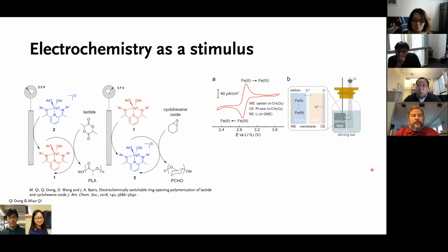For instance, to improve the charge transfer, what Qi and Miao developed was using a carbon fiber as a working electrode. Why did they use carbon fiber? Well, the idea was to increase or maximize the contact area between the electrode and the complex, so as to minimize the time it takes for this reaction to happen. Our end goal is basically like a switch. You turn it on, you polymerize one thing, and then you turn it off, polymerize another. And the latent time here is critical, right? We want it to be as short as possible.